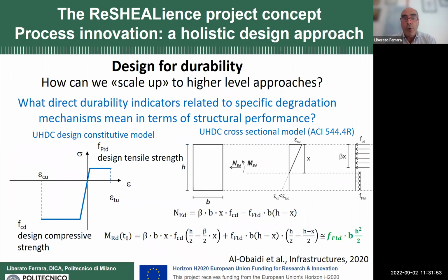So with our ultra-high durability concrete, with our ultra-high performance concrete, the design algorithm that we use is the one that is now recommended in the fib Model Code 2010, but also ACI committees, the 544, which I had the privilege to chair until the beginning of this year, or the 239, are implementing in their reports and in their guidelines and recommendations. Basically, we use the same approach for compression in concrete, and we use a stress block for the tension side, which is guaranteed by the strain hardening capacity. So we perform usual structural design with equilibrium equations for the cross section.